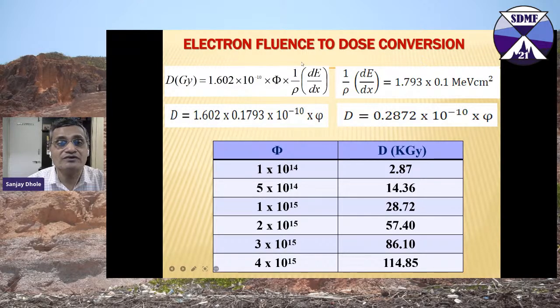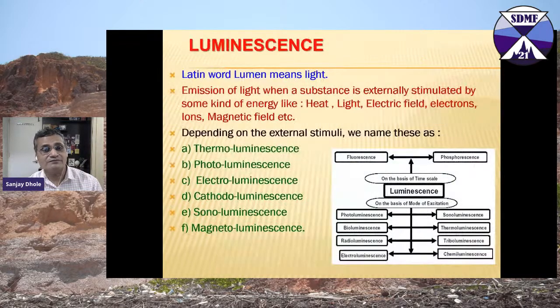This is the stopping power. So the stopping power for electrons can be calculated for a given nanophosphor or the given material. If you put that value and the fluence, then you will get the dose. For example, for a fluence of 10 power 14, the corresponding dose is 2.87, and if you have 4 into 10 power 15, it is 114.85 kilogray. So this is the conversion factor used very often when you are working with electrons. Even in the ion case, it is also possible to calculate.